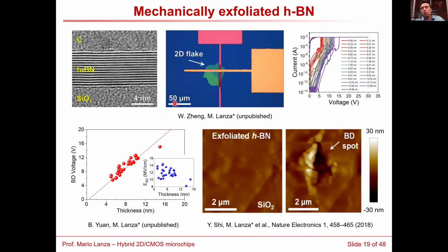So let me show you how we started in this field. The structures that we fabricate are metal, boron nitride, metal. But first, we start with multi-layer hexagonal boron nitride produced by mechanical exfoliation. You can see the little flake here. It has an almost perfect layer structure. And here you can see the sandwich structure.